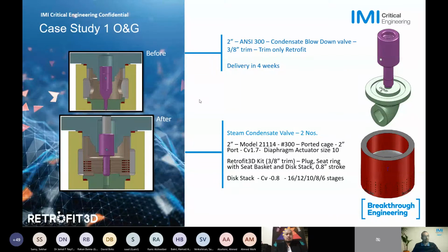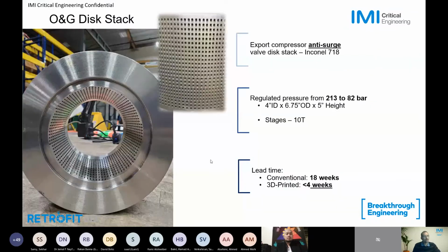This is an example of a little bit of a larger disc stack. This is actually a disc stack that went into a compressor anti-surge application. The material was Inconel 718, and it had a pressure drop from 213 down to 82 bar. So quite a substantial pressure drop, and close to 7 inches in OD, and we included 10 stages, and we were able to deliver this stack to this specific customer in 4 weeks' time. It's not the biggest one that we manufactured, but it's one of the larger trim sets, the disc stack that you see here on the screen.